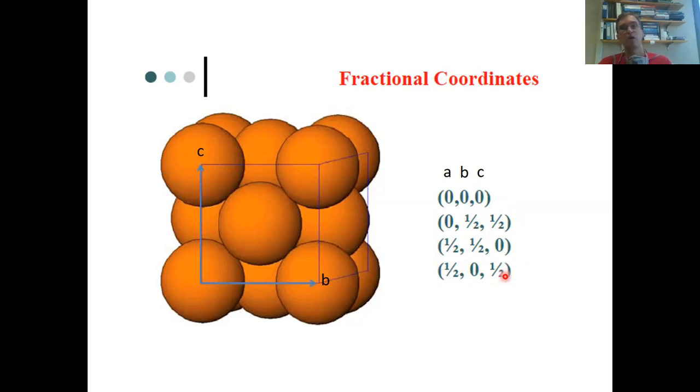Now overall, we have, of course, 6 atoms sitting on the face centers. Why don't we mention the other 3? Again, that is because we can express them by translation along a lattice parameter, either A, B, or C. So that would be, in explicit terms, the atoms that sit on the coordinates 0, a half, a half, a half, a half, 0, and a half, 0, a half.